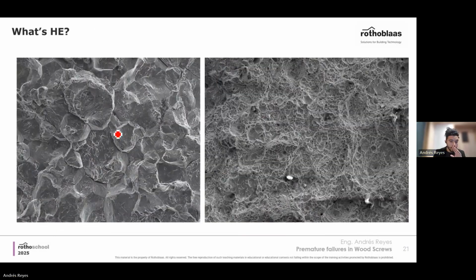you will find in the brittle failure, the one that we saw second, this type of structure. And this is what we call intergranular cracks. So it's on this grain formation, and this is a symptom of a brittle failure. This doesn't necessarily mean hydrogen embrittlement. This means a brittle failure. And finally, at the right, what you see is ductile behavior. So this is a microstructure of a ductile type of failure. The first one is more of the typical breakage that you will see as well when there's some hydrogen embrittlement. That doesn't mean that if you find this, then the cause of the failure is necessarily hydrogen embrittlement. But putting it into context and analyzing it all together, this is one of the things to take into consideration when determining the mechanism of failure.